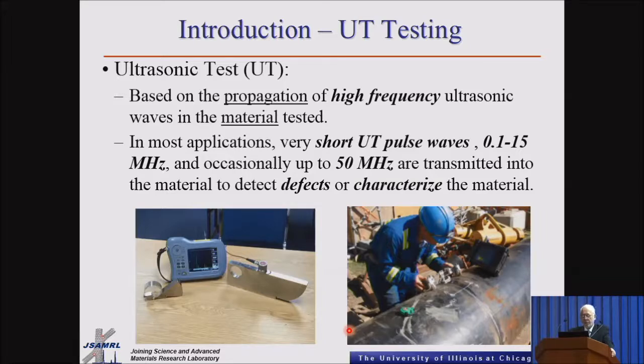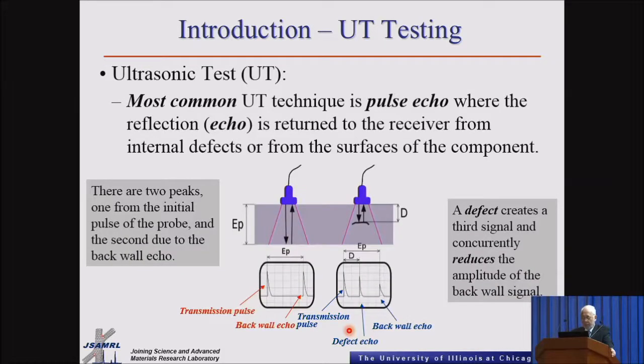high frequency ultrasonic wave through the material, and usually those pulses change in frequency, and they can have a range from 0.1 to 15 megahertz, and sometimes can be up to 50 megahertz. And that depends on the type of defect that you're trying to characterize. And of course, the most popular technique is the pulse echo, all right?